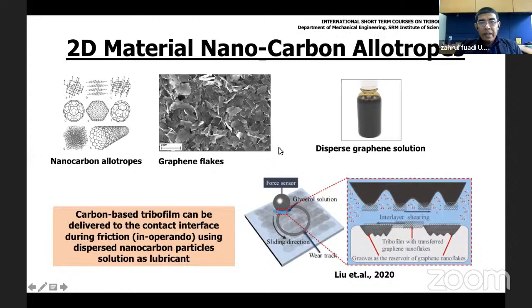So this graphene flake can be dispersed as a graphene solution with some fluids, and then supplied to the contact interface, and then it will form an interlayer, which is this tribofilm with transferred graphene nanoflakes. So this two-dimensional structured tribofilm is formed on the contact interface to fill the grooves of the surface and then provide the surface with low friction and wear.